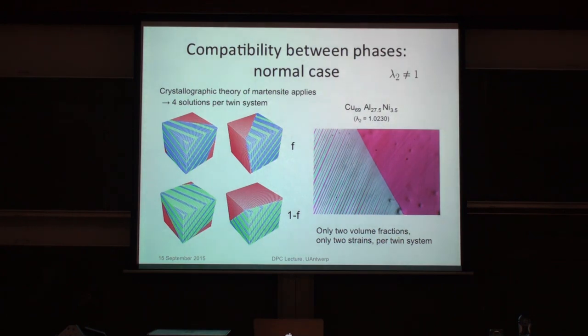Okay, so I'll tell you a little bit more about those materials and some of their applications, but I want to first talk about another development which is very closely related. So I mentioned that this was the microstructure we see at phase transformation. I mentioned there was a theory for it. And there's the four solutions I mentioned. I mentioned that the calculation is quite rigid. They correspond to the two volume fractions, in fact, F and 1 minus F. And so as I said, it's quite a rigid calculation. There's four different normals to the austenite-martensite interface.